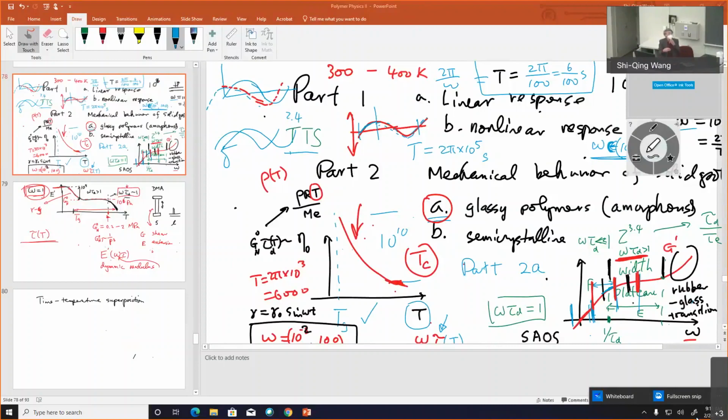So your next temperature choice will be important. If you choose one too big, it's way over there. Of course, it will not overlap with the one. So that's okay. If you don't know this temperature dependence very well, that's okay. You just come back to an intermediate temperature to fill up. Eventually you're going to fill it up, depending on experience, so it may take many temperatures for you to do that. Okay. That's superposition in that sense.